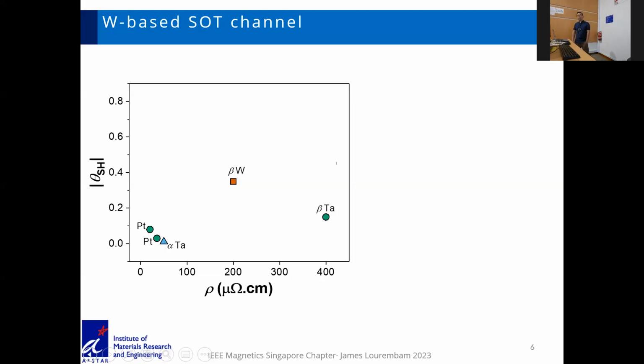So there have been many developments in this area with regards to development of a good spin Hall angle system. While there are many interesting materials, with regards to development of these materials on a 200 or 300 millimeter wafer platform, we are restricted to basically three materials, which are tungsten, tantalum, and platinum. Out of these, beta phase tungsten has the highest spin Hall angle. But one would also try to optimize the resistivity in the channel, because a higher resistance would require a higher voltage that might not be suitable for the CMOS requirements.